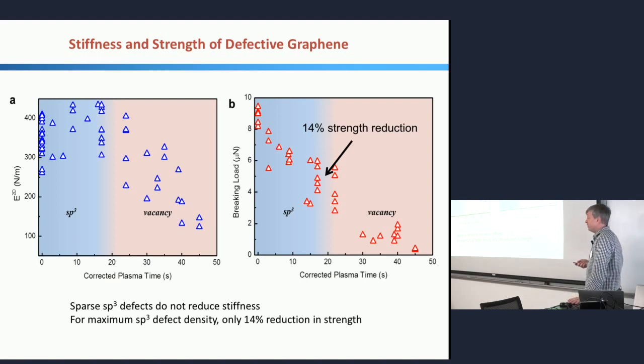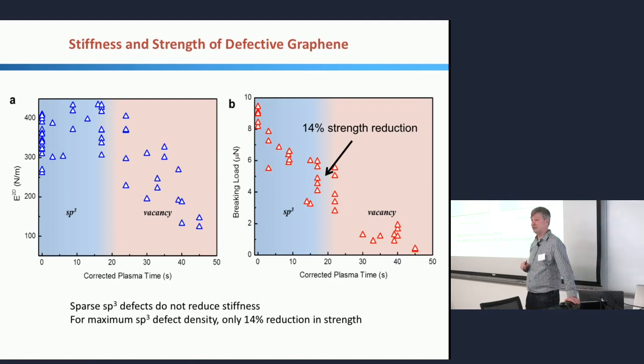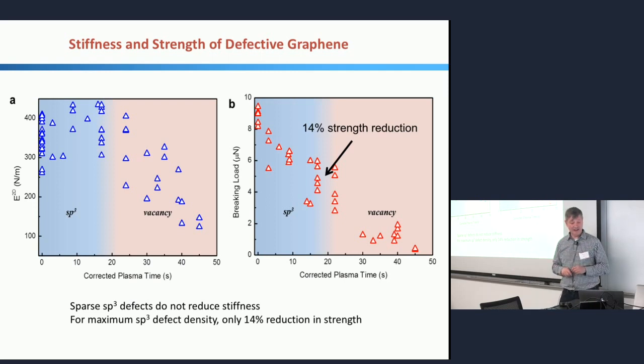But again, because the Young's modulus is constant here, we decided that we can still use our nonlinear mechanics model, at least in this sp3 regime. Out here, it's another ball game, and that still needs to be done more rigorously. But at least at this point, when we're just putting in these sp3 defects and not actually removing much material, this reduction in breaking load corresponds to a reduction of only about 14% in the breaking strength. So I think this tells us that we can put a lot of cross-links, a lot of point defects into graphene, as long as we're not making macroscopic holes, but holes the size of a few atoms. We can still maintain very high strength.